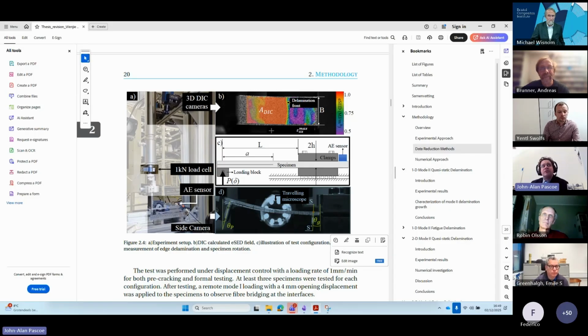Yeah, but I think what has been analyzed, and it's common also for the DCB specimen, is that you do see this kind of thumbnail shape, because at the edges of the specimen, due to edge effects, you get a little bit of closure, if I remember correctly. So typically in the center of the specimen, the crack always grows a little bit faster than at the edges. And of course, if you have asymmetries in your loading setup or in your layup, then that all gets exacerbated, and all of these just get even worse.